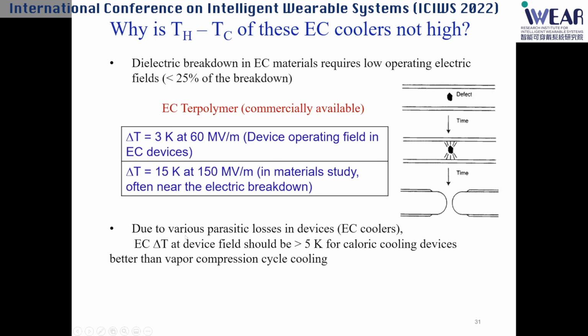Also, due to various parasitic losses - if you have a device with an enclosure and many other things - with only 3 Kelvin of EC effect, you have to overcome those parasitic losses. A lot of system modeling also shows that for an EC cooling device to be competitive with the vapor compression cycle, the temperature change must be higher than 5 Kelvin. So you can see in all the EC cooling devices, the temperature change in the device is actually about 2 to 3 Kelvin. That's one of the reasons why the performance isn't so good.